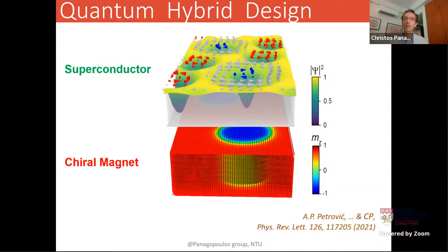A major challenge, however, is that superconducting vortices and magnetic skyrmions do not simultaneously appear in a material, let alone interact. So to get around this problem, we developed a hybrid material combining niobium, which is a very well-known S-wave superconductor, with an atomically precise magnetic multilayer made of iridium, iron, cobalt, and platinum. This is a completely new material architecture. It is essentially a stack of magnets and the superconductor.